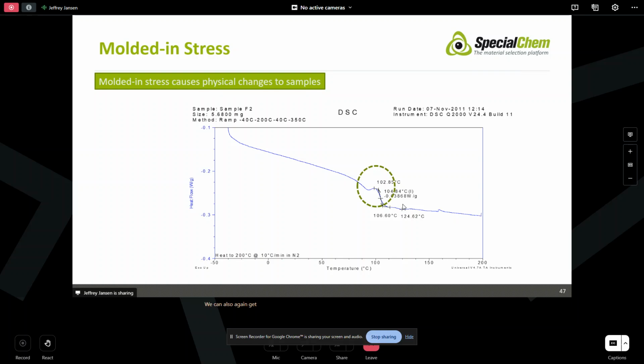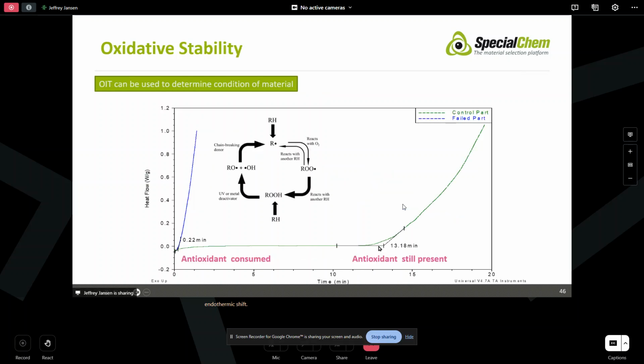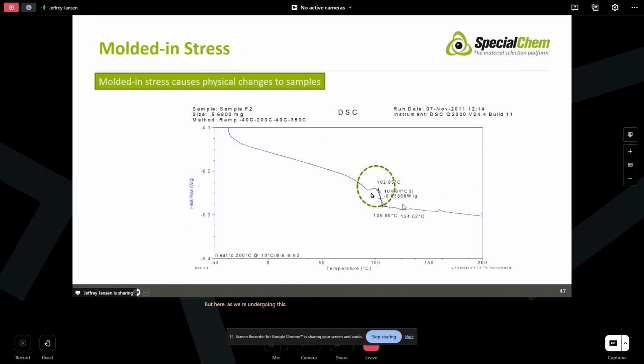We can also, again, get a red flag. It's not necessarily a smoking gun, but a red flag whether the material has molded-in stress in it or not. And if we have this, you can see the material starting to undergo, as it goes to the glass transition, this endothermic shift downward. I think I said this was an endothermic shift. I apologize. Oxidation is an exothermic shift. I apologize for that statement. This would be exothermic, that transition, that reaction with oxygen. But here, as we're undergoing the glass transition, that endothermic shift, we see this kind of phase upward. That kind of upward shift then is the material, the molecules, reorganizing themselves, and it's a clue that this material has possibly been molded in such a way that there is molded-in residual stress.